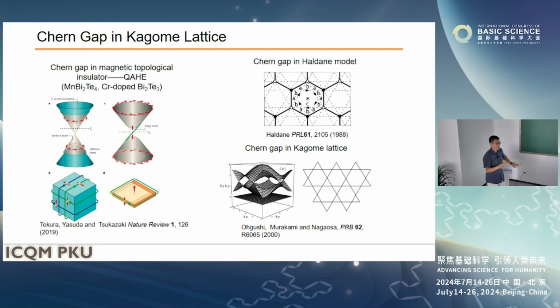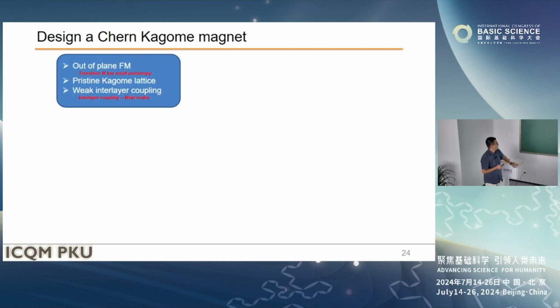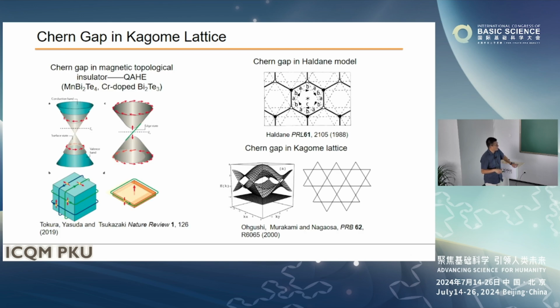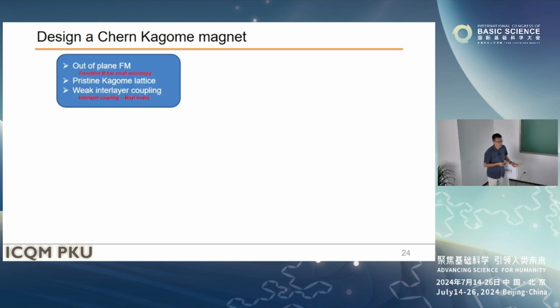Even without a staggered magnetic structure, for a Kagome lattice in 2000, with SOC and time reversal symmetry breaking, you have this single band crossing. With time reversal symmetry breaking, this band crossing will open a small gap, and this gap is topologically non-trivial. And you see, if the Fermi level is around here, you should see a quantum anomalous Hall effect. So what should we do? We are motivated by this model, right? We try to find some real materials which contain a Kagome lattice, and the lattice is formed by magnetic ions. And fortunately, we may find some interesting physics.